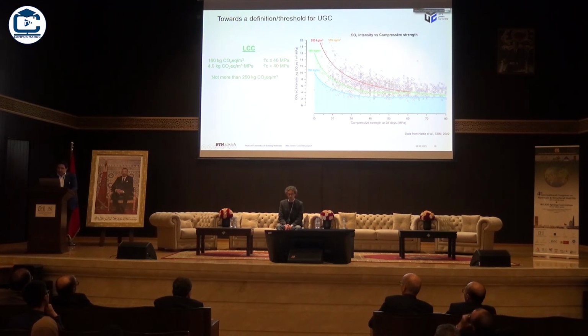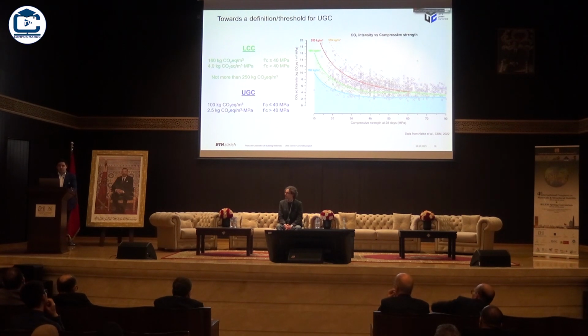So the green area would be low carbon concrete, limited by these values here, and ultra-green concrete would be lower than 100 and then stay stable at a certain value of CO2 per cubic meter per megapascal, to not penalize high performance material. It looks very challenging because, as you see, there are not so many points in the ultra-green concrete area. This is basically because of how the codes are made now in Europe.